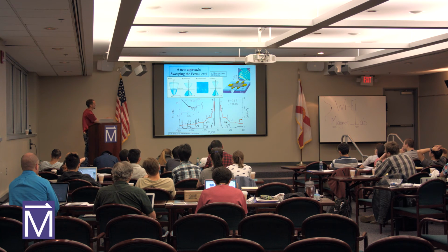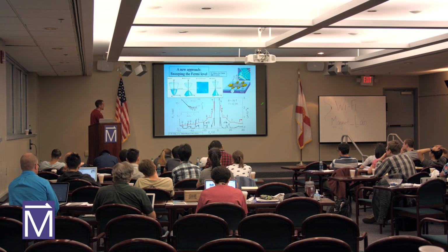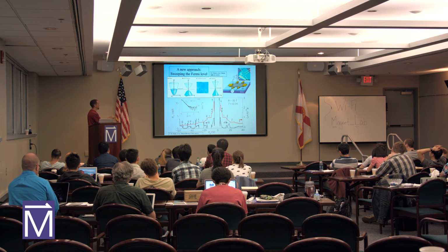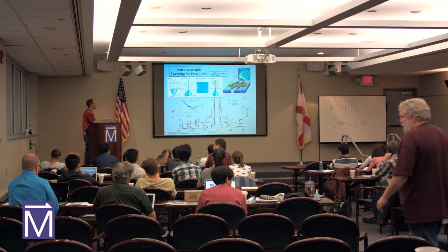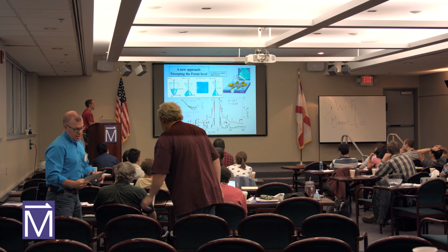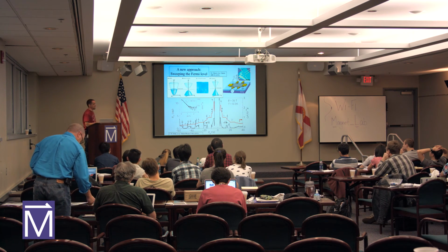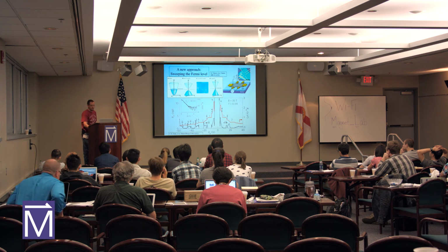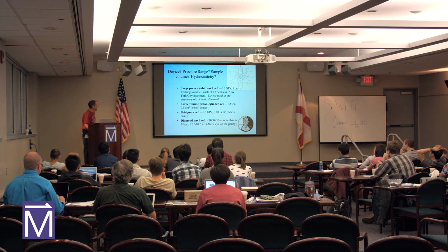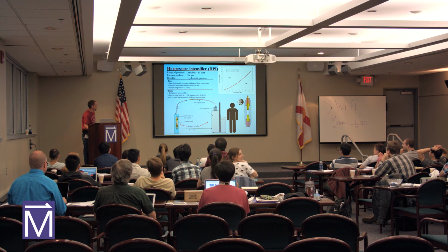But by measuring the Hall effect, we can also see the fractional quantum Hall effect at high fields, not by sweeping up the magnetic field, but by going up to 35 Tesla, sitting at a constant magnetic field and low temperature, but by sweeping the electric field across the sample, by sweeping the gate across the sample. Okay, this is a kind of a more modern approach that people are taking to exploring the materials in these devices. Okay, and I promised Renee I would finish, so I'm going to skip all the high pressure stuff.